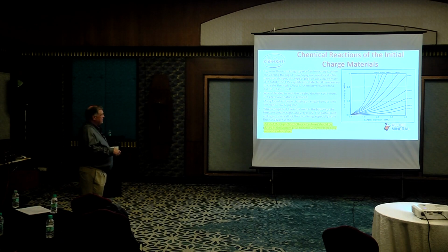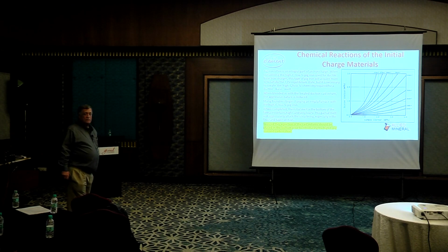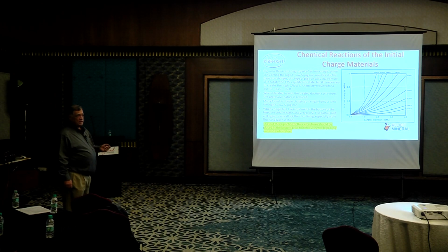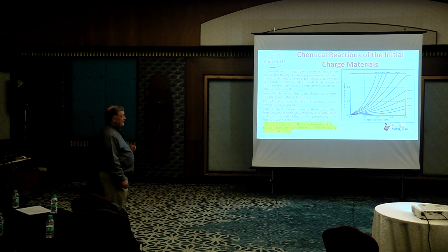So this is just telling you, to avoid. This is the carbon, silicon equilibrium, which we've seen many times, kind of where temperature lies and what happens with the aggressiveness. So if you have a low carbon, low silicon, you're going to have issues, if that's what you're melting in steel. If you're putting pig iron and you have high carbon, low silicon, which is typical, then you need to put some ferrosilicon in the bottom of that furnace because you need to stabilize that metal as quick as possible. Otherwise, it will very easily take it from the lining. And that's all silica, okay? No matter whose silica you use, that is an international fact.